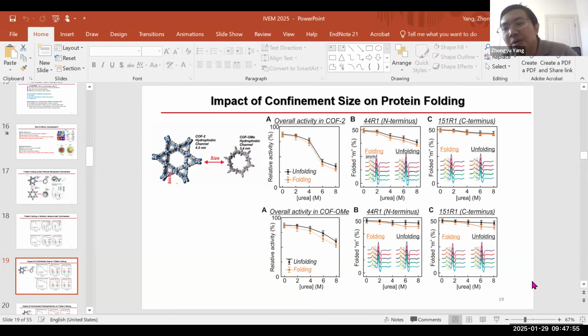However, we really don't know the diffusion rate, the diffusivity of the small substrate, because the substrate has to diffuse in, get cut, and then be released so we can measure the activity. That we have to assume, because the substrate is quite small, less than 1 nanometer, and we assume they can go in and out. But we're looking for a theoretical or NMR measurement of the diffusivity of that substrate through these MOFs.